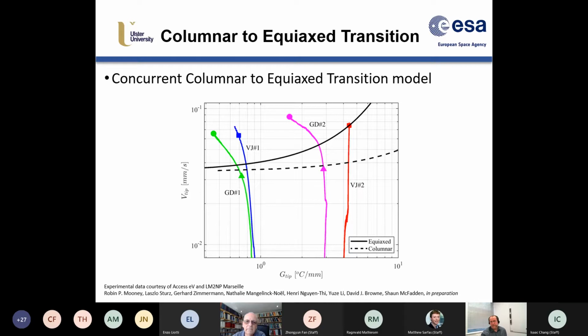And what we found was that it was very hard to get a single set of nucleation parameters for the Hunt diagram that would satisfy all 4 cases. It was practically very difficult, I would say impossible to do. What we were able to do, though, was simulate faithfully the CET transitions in all 4 cases using a consistent set of parameters, using the combined concurrent columnar to equiaxed transition model.